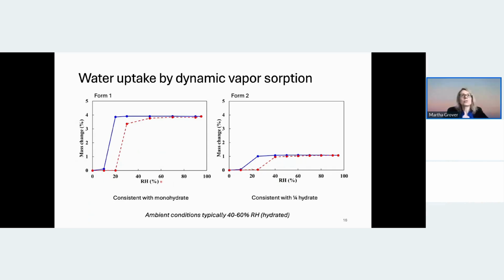But where we did see a major difference between form 1 and form 2 was on water uptake. So we performed a dynamic vapor sorption experiment. And so we vary the relative humidity from 0 to 100% and observe the mass change. And similar to what we saw for the TGA of form 1, there was a mass change that would occur, with some hysteresis here, but between, say, 20 and 40%. And the mass change was 4%, which is consistent with the DSC, consistent with having a monohydrate.